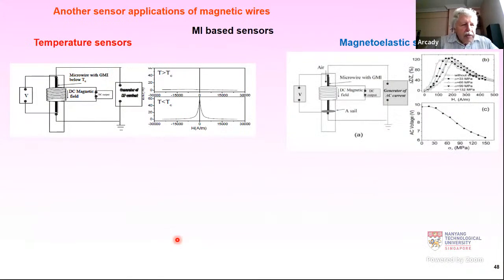So now the group is also developing different sensors, for example, a temperature sensor and a magnetoelastic sensor. For example, in the case of the temperature sensor, the magnetic impedance disappears above the Curie temperature. And in this case, we can relate measurements of magnetic impedance with temperature. Here we apply stress, and you can see how it changes the magnetic impedance. And this is a kind of calibration proof. And if we fix the magnetic field at some point, we can measure the AC voltage from the pickup coil and see its dependence on applied stress.